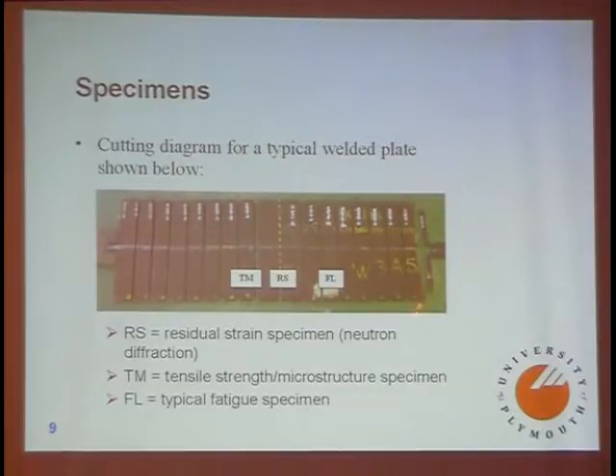So we get these plates. These are 1 meter long by now 300 millimeters wide, and we cut them up. And again, there's always approximations to what you can do. You need a fairly big specimen to be reasonably certain that you've captured the residual strain field that is representative of the full-size plate. And so that is the residual strain specimen there. It would be nice to test fatigue specimens of the same width, but unfortunately the testing machine won't do that. So then you figure that, well, if I keep these as 40 wide and don't change the length there, there's a sporting chance that the transverse residual strain in that direction is moderately untouched, and with any luck that will be the strain that will matter more to the weld rather than the sum of the principal strains, but you don't know the answer. So these are fatigue specimens, and that one there was used for microstructural analysis, as you might say.